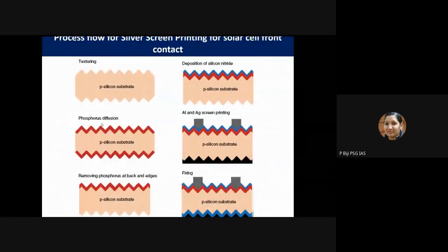Now, if you see the process flow adopted for screen printing of the solar cell front contact, I don't want to explain all this texturing, diffusion and all again. In this case, the silver paste also contains aluminium. This aluminium and silver based paste will be screen printed, and then during firing, the silicon nitride will open up, and these metal lines will be in direct contact with the emitter layer. That's how you get very good adhesion, and the conduction happens very efficiently.